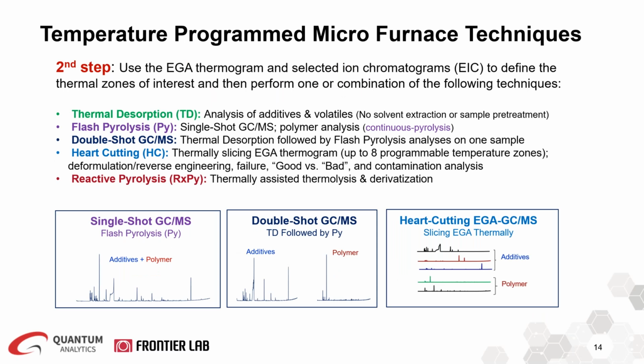After obtaining your EGA thermogram, you can analyze the peaks using the F-Search EGA MS library. If it's needed to further analyze the sample, then EGA guides you to the next step. You can perform thermal desorption, which is used for analyzing additives and volatiles. However, the key point here is that you are thermally extracting all the additives and volatiles from the mixture. So any sample preparation or solvent extraction step is eliminated.